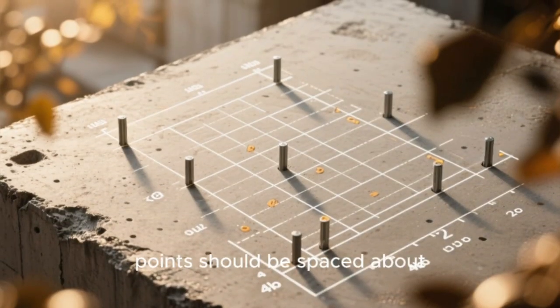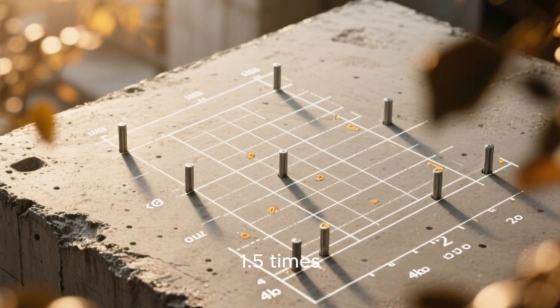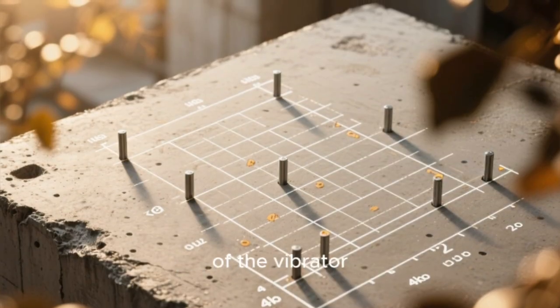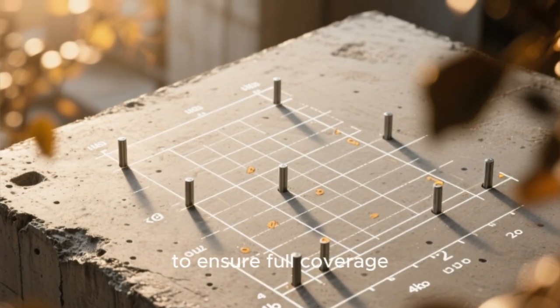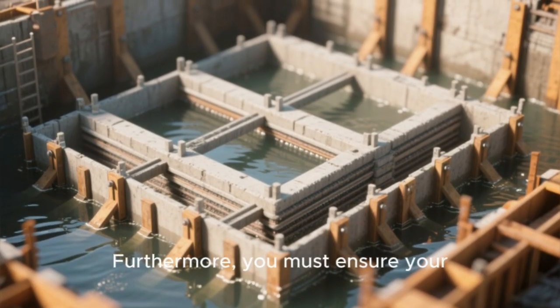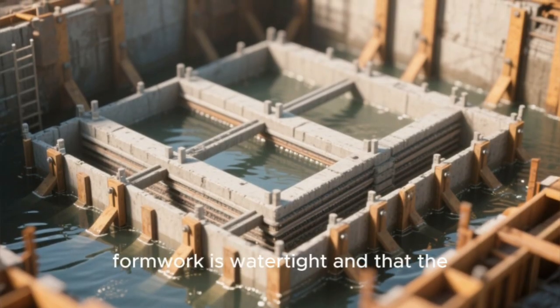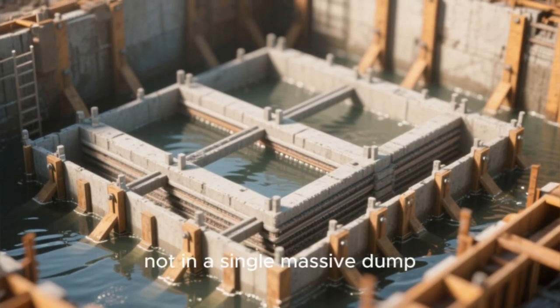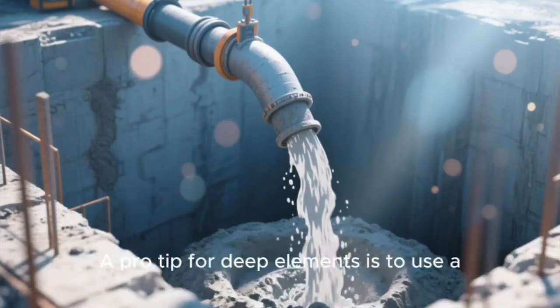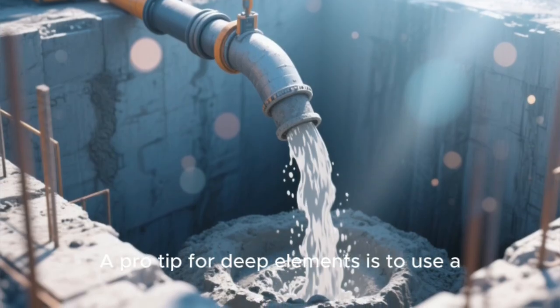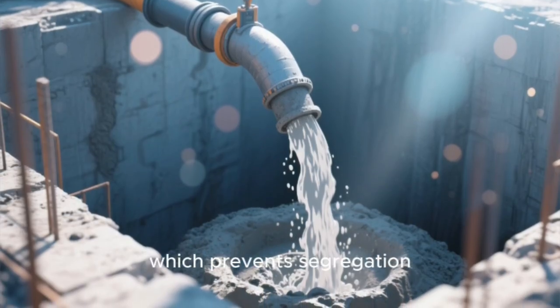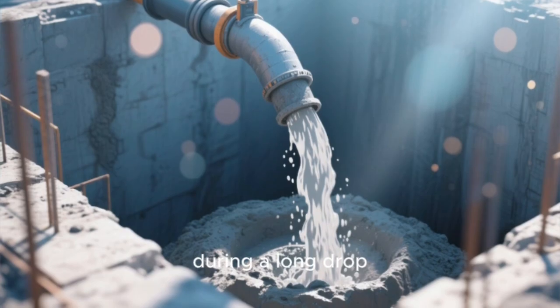The insertion points should be spaced about 1.5 times the radius of influence of the vibrator to ensure full coverage. Furthermore, you must ensure your formwork is watertight and that the concrete is placed in layers, not in a single massive dump. A pro tip for deep elements is to use a tremie pipe to place concrete, which prevents segregation during a long drop.